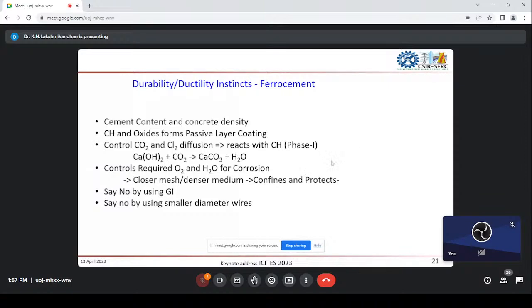Similarly, the calcium hydroxide and the oxides are all chemicals that protect the steel as a passive layer, and they compensate and protect the steel. In a similar way, if you can control carbon dioxide and chloride diffusion, which normally react with the calcium hydroxide, then the corrosion cannot start, or the durability of the structure will be very, very high.